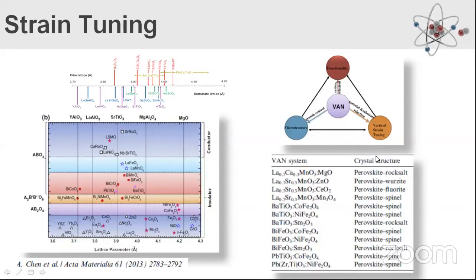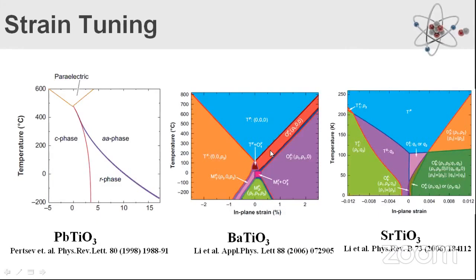By tuning the strain along the vertical axis and the strain along the horizontal axis, how does strain affect a ferroelectric or perovskite material, as shown here? Lead titanate is one of the well-known and robust materials. Without any strain, this is the ferroelectric Curie temperature. Above this temperature, it is paraelectric, and below this temperature, it is ferroelectric.